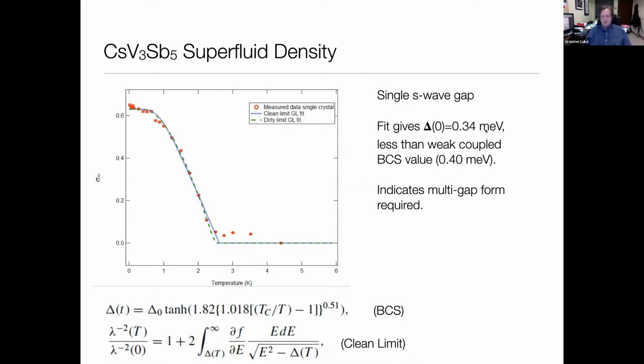We get a gap at 0, which turns out to be about a third of a millielectron volt, and this is significantly less than the BCS value of 0.4 millielectron volts for the TC of 2.5. The fact is that in weak coupling BCS theory, you get superconductivity for an arbitrarily weak interaction. And so you can't have a smaller gap than the BCS gap, because that's the weakest one that comes out of the theory. If you have a stronger interaction, you can get gaps that are bigger, but you can't get a smaller one.